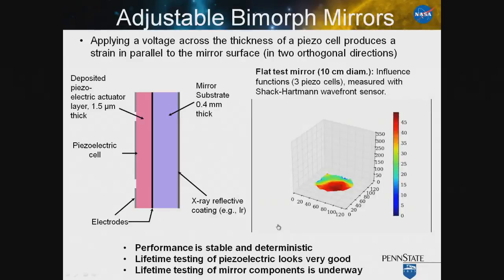What you can see here is one of the test optics that we sent from Penn State to the Smithsonian Astrophysical Observatory. And you can see here, as we progressively increase the voltage, the deformations that are associated with actuating 3 of those piezoelectric cells. And we're able to achieve deflections of several microns at modest voltages. For the most part, we're targeting voltages under 10 volts to simplify not just the ability to put large numbers of correctors on, but also drop the required weight associated with the electronics to do this.